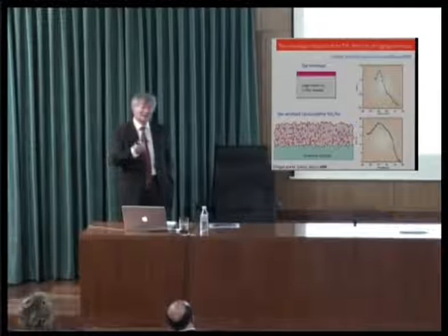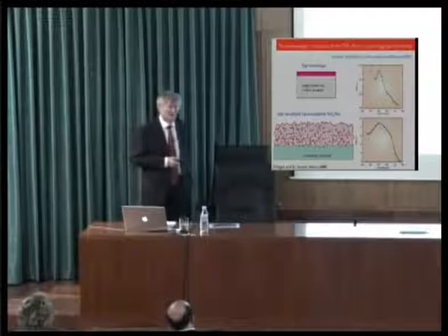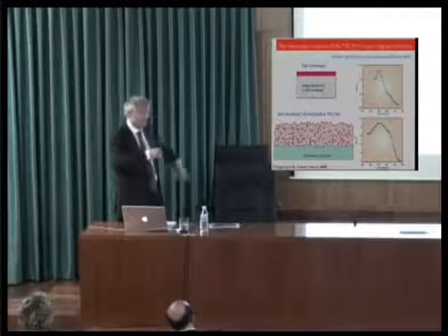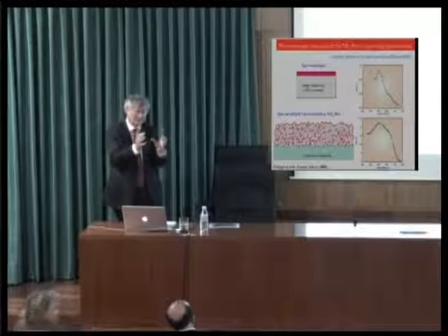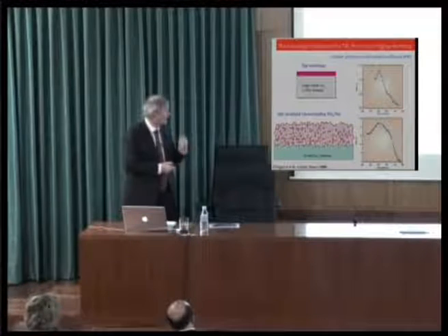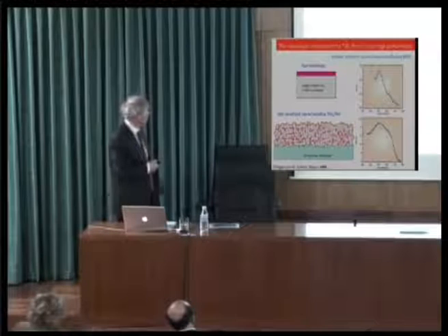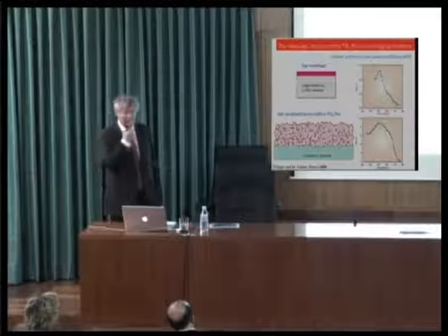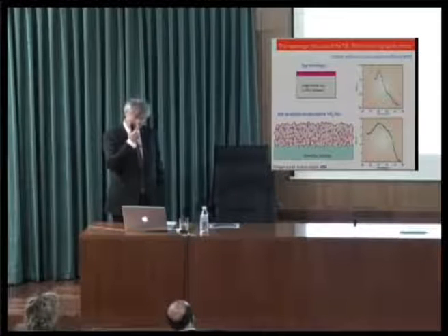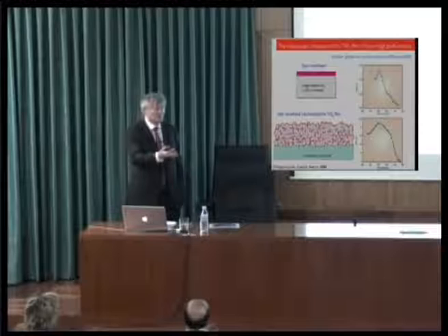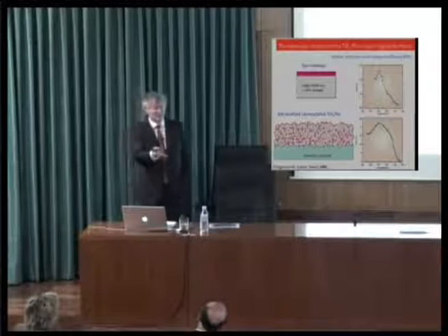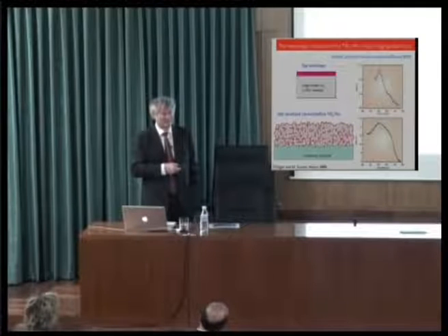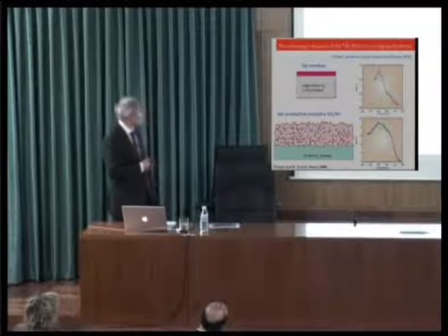There's no electric field that will help you to separate the charges. The reason why there's no electric field is that these particles are surrounded by a high ionic strength, screened. And so the field is screened, and so there is no field that drives the charge separation. It's only done by diffusion. So if you write the continuity equation, you can forget about the migration term. There's hardly any migration involved, just diffusion. And so why can we collect?